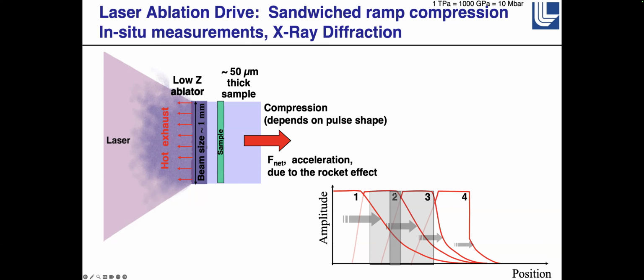And so when you get to sort of this 2 wave, you can have a steady ramp compression wave sitting in your sandwich target, and we can generate that on the order of 5 nanoseconds. So this is the technique that we use, and then we can measure the velocity of either the interface or the free surface velocity to get the pressure that we're at.